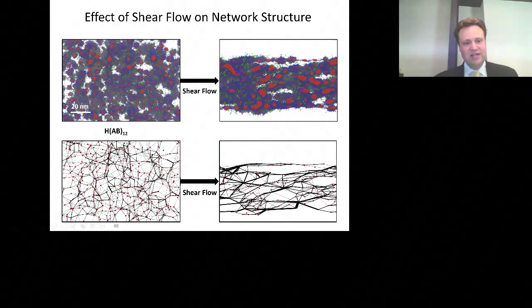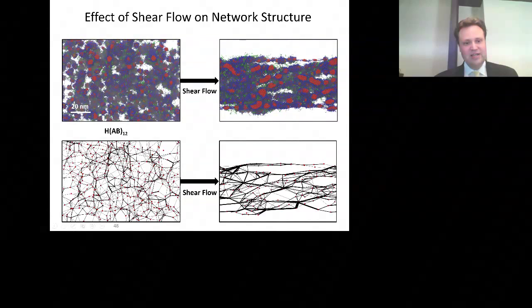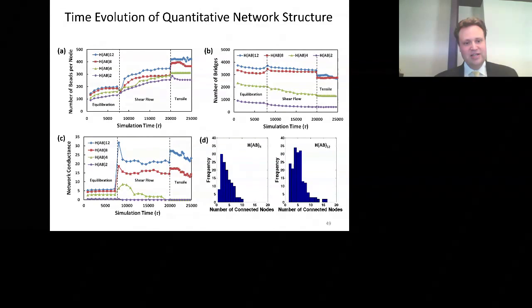So the way we plot the data here is the thicker the lines, the more connections there are. So the shearing not only increases connectivity both before and after, but also increases connectivity in one direction, so creates an anisotropic structure. So the fiber becomes very strong in the fiber direction, very connected, and there's some connectivity out of plane in the orthogonal direction, but of course it doesn't increase significantly under shearing. So the shearing creates, we think, some very important mechanical traits. And now we talk a little bit about the design aspect.